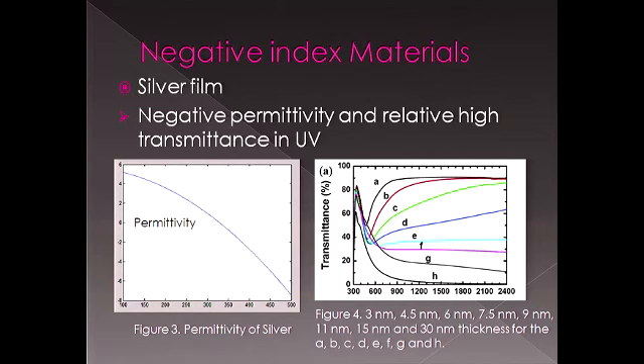But fortunately, we can find some materials like silver, gold, and copper, which show negative permittivity in some wavelengths. And in those materials like silver, the magnetic permeability is not so important. So what we care about is only the permittivity. Only if we can find negative permittivity can we use it to make a superlens to reconstruct the evanescent wave. So here is the permittivity of silver. We can see that when the wavelength is larger than about 300 nanometers, the permittivity becomes negative.